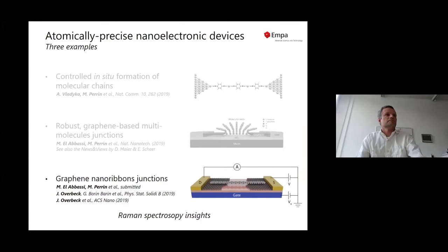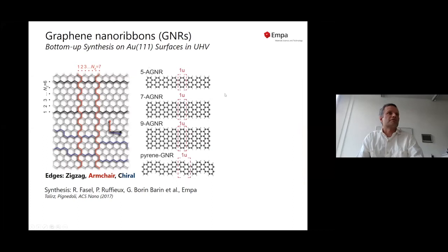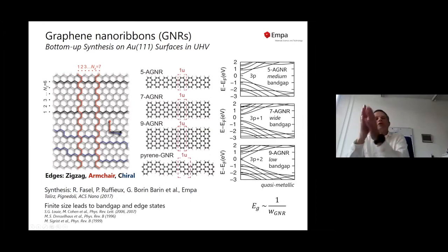So you see here a couple of examples of these different types of nanoribbons. The five-AGNRs will be those ones here, right? If we count the atoms starting here: 1, 2, 3, 4, and 5 atoms here. Then 7, 9, and so on and so forth. And then the length of this nanoribbon is also given in the number of repeating units that one has there. So the interesting thing is that those objects are again synthetic objects where essentially the size can be controlled. Not the length, this is not so easy to do, but the width can be very well controlled by choosing the appropriate precursors to get there. And that means that a lot of control on the electronic properties can also be achieved like that.